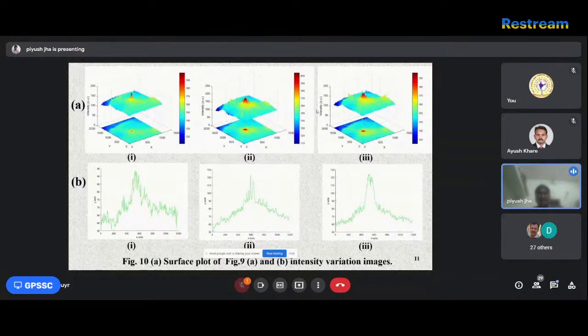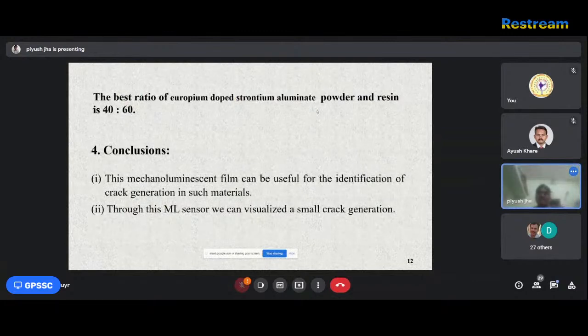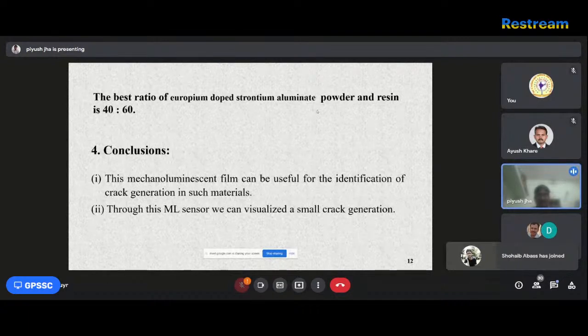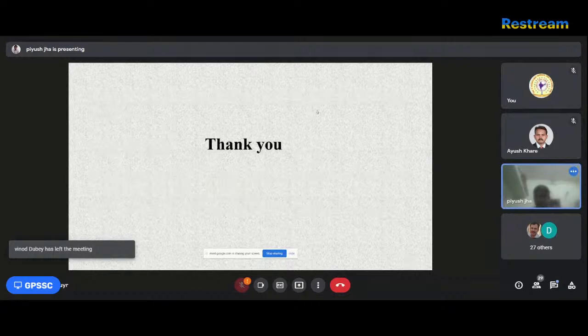In this study, we also found the best mixing ratio of europium-doped strontium aluminate phosphor and resin is 40:60. It gives better adhesion strength at the interface between the ML sensor and the glass plate. If the adhesive strength is sufficiently higher than the fracture strength of the ML sensor, it shows superior tracking performance for fracture generation. And in conclusion, this mechanoluminescent film can be useful for the identification of crack generation in such materials. Through this ML sensor, we can visualize a small crack generation which is poorly visible with an unaided eye. And the ML sensor is able to detect potential destructions such as active cracks, real crack propagation, and mechanically weak points. Thank you.